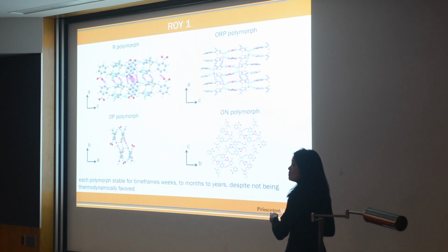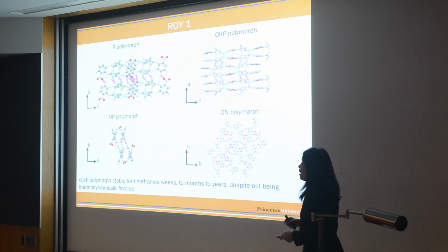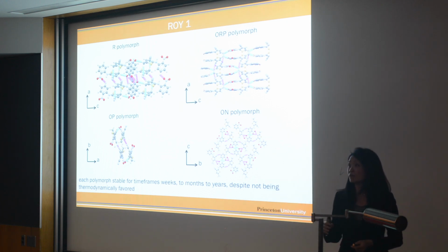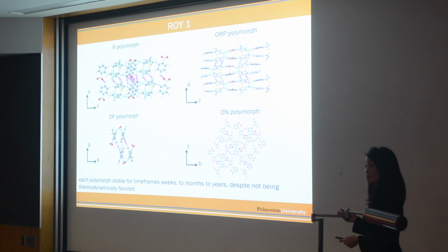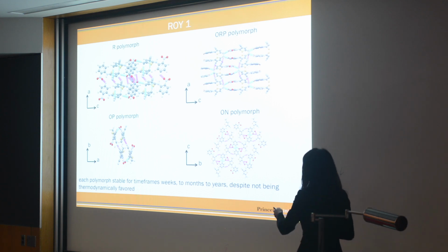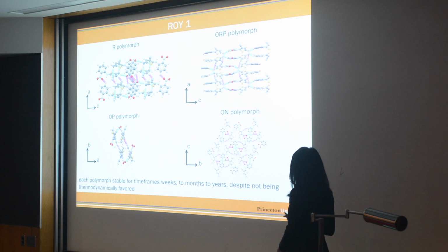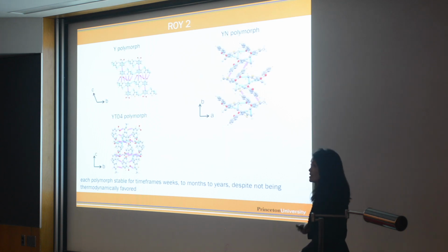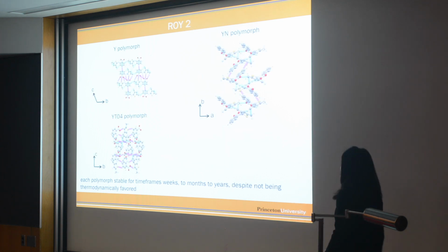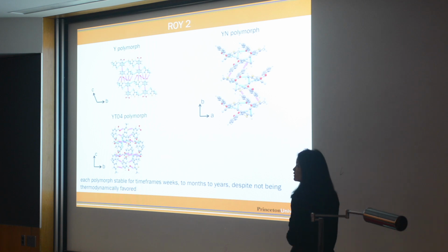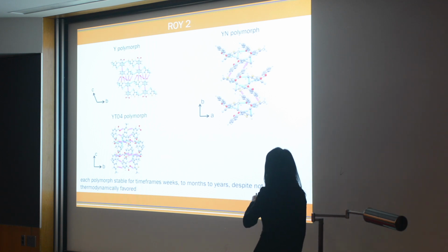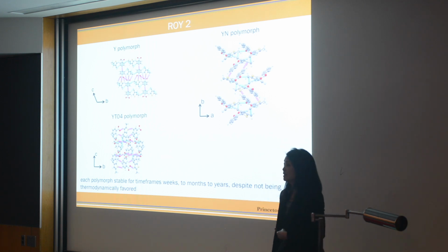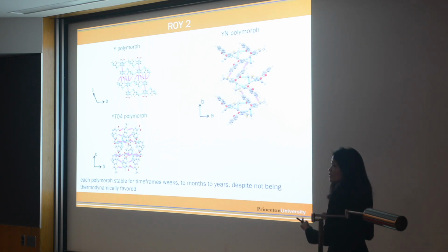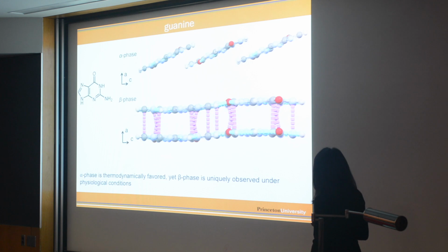And again, consistent with our framework, all of these polymorphs can be stable for weeks, months, years. Okay? And we believe these short contacts are stabilizing these different polymorphs. ROY2 is the second conformer. It too has different polymorphs. And again, all these polymorphs have short contacts. And we believe that's consistent with why these different polymorphs are again stable.